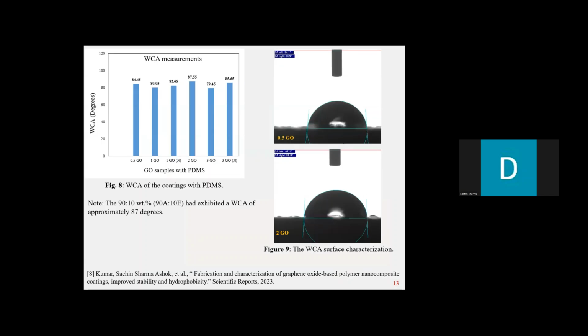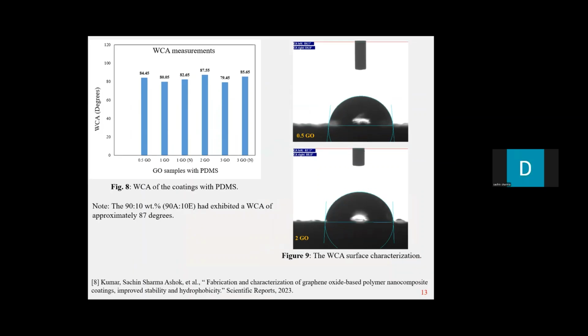Figure 8 illustrates the water contact angle measurements for all the coatings with the inclusion of PDMS. And the first thing I would like to talk about is the base. I also calculated the water contact angle for the 90:10 weight percentage of the polymer matrix, which was the acrylic to epoxy ratio. It exhibited a water contact angle of approximately 87 degrees. So it clearly shows that the base itself is not hydrophobic.